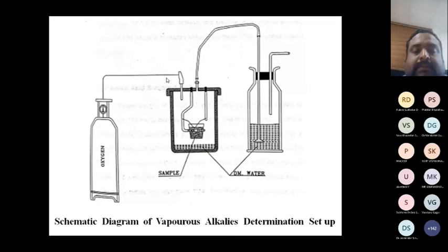This is one of the characteristic techniques I adopted for my research project. So far we have seen the water soluble and ammonium acetate soluble fractions, assumed to be highly vaporous. Whatever salts come out are assumed to be vaporous. Instead of going for the indirect method of water soluble and ammonium acetate soluble, why don't we measure vaporous alkali straight away? That is the approach I made. See, this is an oxygen bomb, the bomb calorimeter. There you take the fuel, fill the bomb with oxygen and burn it. After burning, I collected all the flue gas after completion of the bomb calorimeter reading. I collected all the gases and passed them through DM water. Both this DM water and the bomb washing, I collected as samples and analyzed for vaporous alkali.